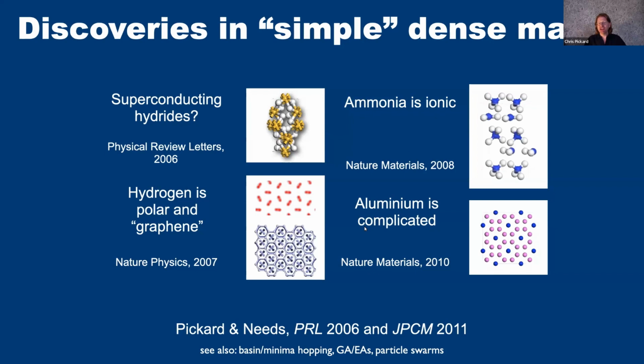And then at even higher pressures, at terapascal pressures, we made a prediction that aluminium would become a complex host-guest phase, which is very interesting to the people doing very high pressure dynamics experiments, for example at the National Ignition Facility in the US, where it had been thought that maybe when you kept squeezing matter, it just got simple and close packed. There's lots of emerging information from these calculations that actually, no: as you bring in the different core levels of your atoms, you actually get quite complex structure emerging.